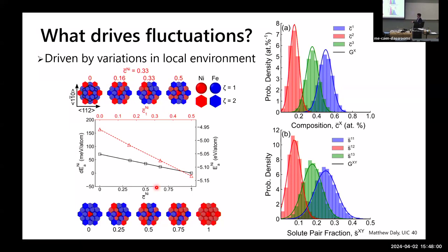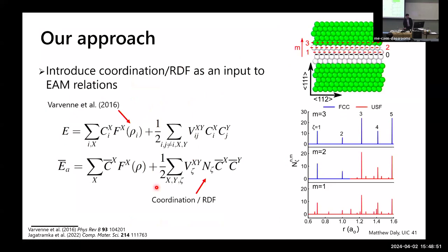Well, it turns out, and again, the paper which is referenced, I left the key references slide somewhere else, the statistics of this can actually be analyzed analytically. Basically, you can make some arguments, and that's what's being shown through numerical simulation here, that if you know how many atoms you're sampling and you know the overall composition of the alloy that you're dealing with and it's randomly arranged, you can predict, with an arbitrary number of elements and arbitrary composition, the statistics of the local environments that you might sample. And you can also predict the bonding environments that you might sample. So the pairing between first and second nearest neighbors or third nearest neighbors or whatever nearest neighbors you might be interested in. So with relatively modest analysis, you can capture these statistics just from direct analysis. You don't need to do any fancy simulations. So that covers the chemical environment, but what do we do about the energetic environment, the energy? We need a map from chemical to energy.